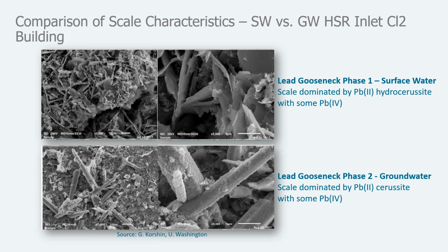Then under phase 2, the scales had to change over. We still see some hydrocerussite formation, but we see the development of these cerussite crystals, minerals that, when exposed to the higher DIC groundwater, were predicted. These are more soluble at the pH that they were at, so that's why we saw higher lead release. We saw higher particulate release as the scales actually had to change their crystalline structure in exposure to the different chemistries.